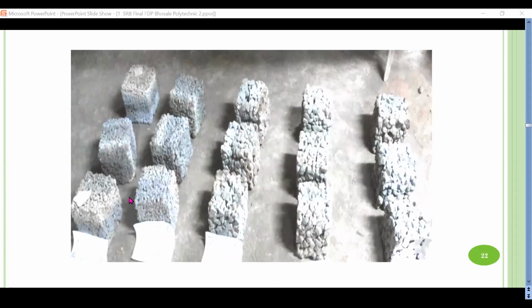What I told is we can use 10 mm to 20 mm. So you can see here a few cubes which are made using a smaller size aggregate, 10-12 mm aggregate, whereas the other cubes are made from 20 mm size aggregate. The voids will differ, but the interconnected voids should be maintained so that water will percolate through it. That is the main aim, the main idea behind making a proper proportioning of pervious concrete.